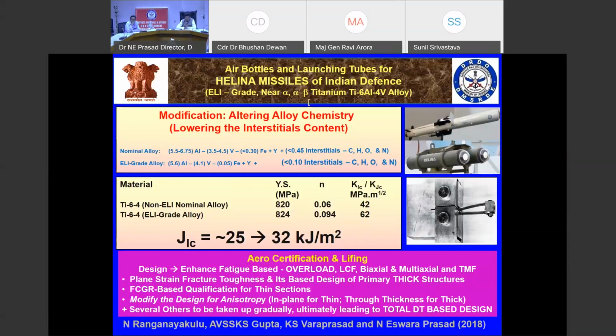This is called extra low grade because the low interstitials will actually decrease the yield strength, but they tremendously improve the fracture toughness. But by heat treatment of this titanium alloy, even at the low interstitial, we could almost retain the yield strength and improve the fracture toughness by 50%. That's the biggest achievement. To evaluate that, we had to generate a special fracture mechanics methodology based on J integral. So 25 is the absolute number, 32 is the achieved number. That means 25 would have given 52 to 55, and 32 is the achieved number, which gives 62 MPa root meter when we convert this. This has been the qualification mark for the HELINA missile material, which is made from titanium 6-4 with an extra low interstitial content.